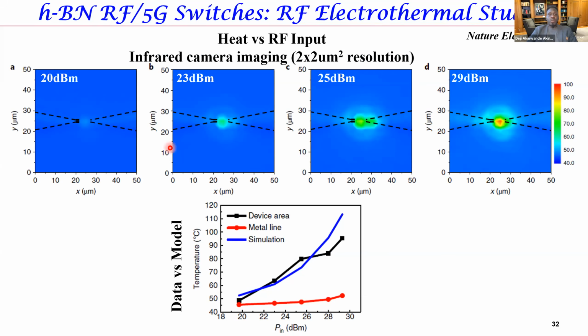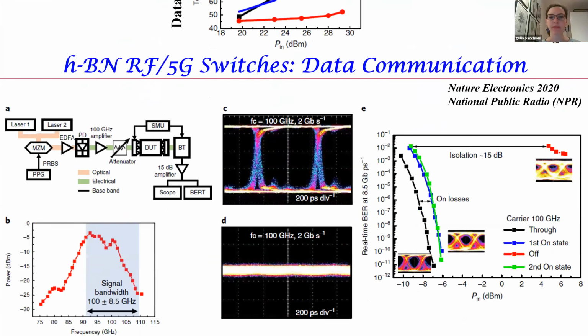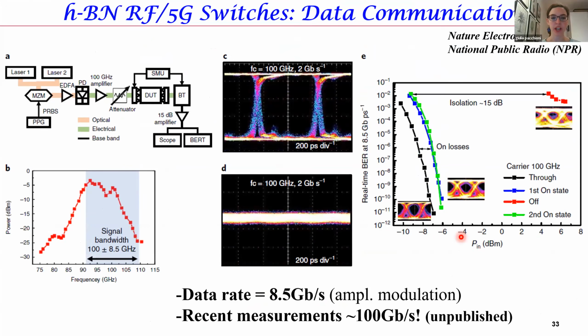This is just to show that we can actually measure the hotspot temperature using an infrared camera on a working device as a function of the power input. So you can see the hotspot develops where the device is located, which is the middle of the bow tie region. And to cool it off, the best thing is to put it on a diamond substrate. So all the devices now that we make are on diamond substrates because of the thermal conductivity of diamond compared to silicon oxide.